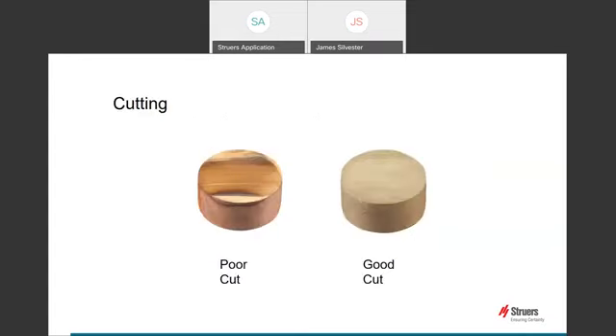If we look at the thermal damage effect between a poor cut compared to a good cut, we can see the image on the left is burnt and discolored. This is usually down to incorrect cutting wheel being used, or insufficient cooling, or cutting too fast. Cutting with the optimal cutting wheel for the material is the critical first step of sample preparation. So let's have a look how we select the correct cut-off wheel.